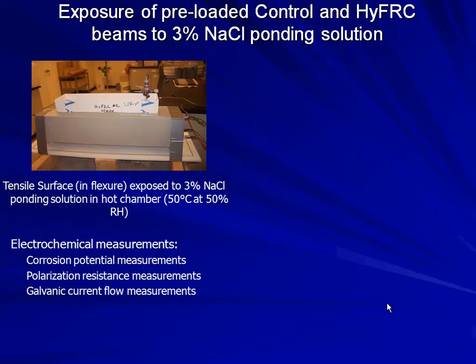Then we ponded that. That's when we did all this environmental testing, this corrosion test and so on, because Berkeley has had a history of that for many, many years, starting with Professor Mehta, looking at durability. So we have all the equipment to do these measurements for durability studies. We looked at electrochemical measurements and so on. We ponded exactly that top surface, the tensile surface that was cracked, with a chloride solution to look at corrosion. I will not go into these electrochemical measurements, but I can mention that the corrosion rate was much lower in the hybrid compared to the control specimen.